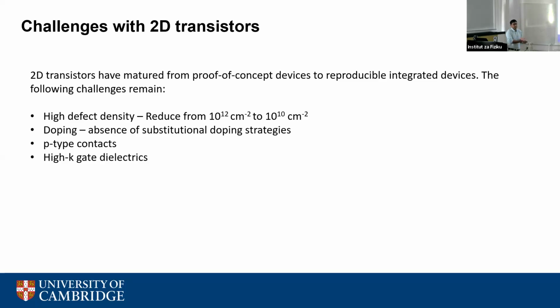And if you ask everyone in the community, they will say MoS2 is N-type. But no one knows why MoS2 is N-type. There's no reason for it to be N-type other than defects or the contact which pins the Fermi level. So we really need to reduce the defect density to around 10 to the power 10. And there's been some work using flux growth, which has enabled this.